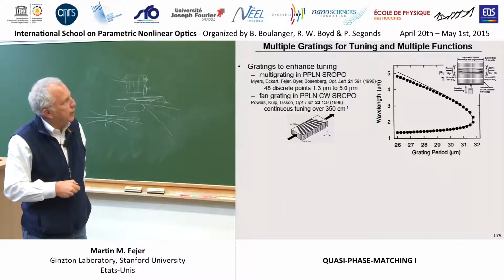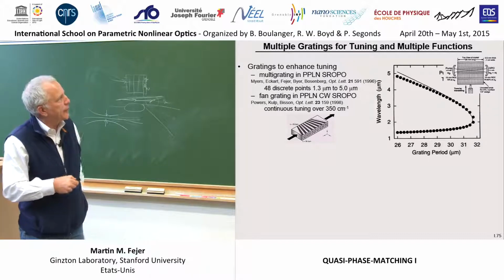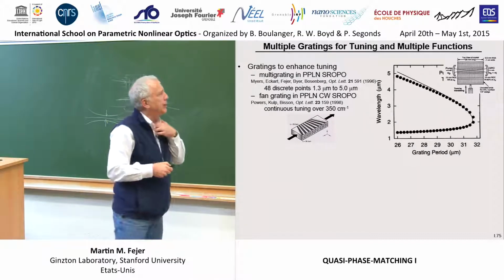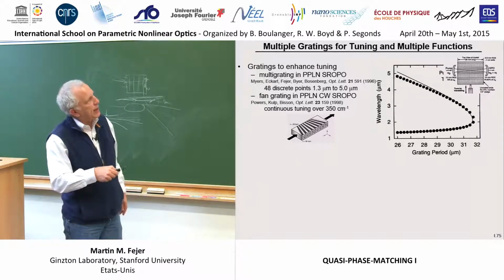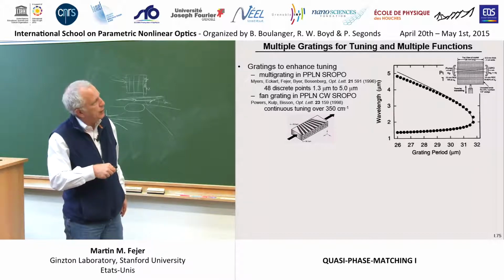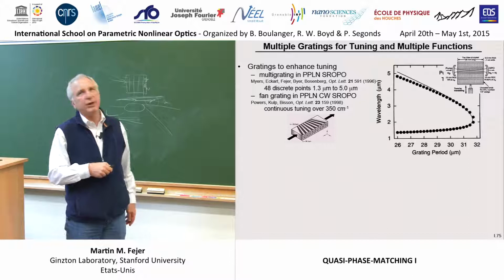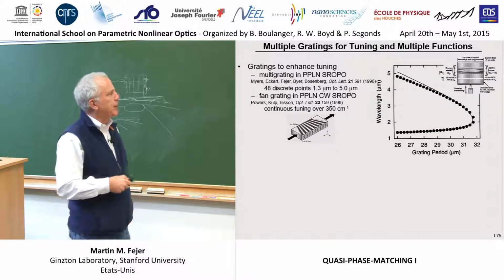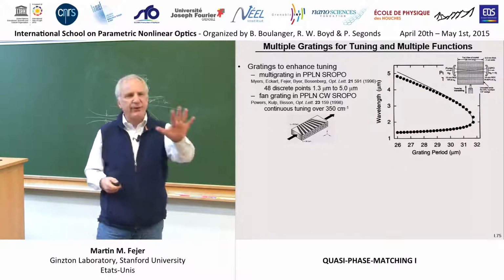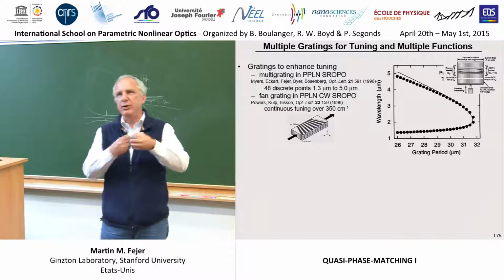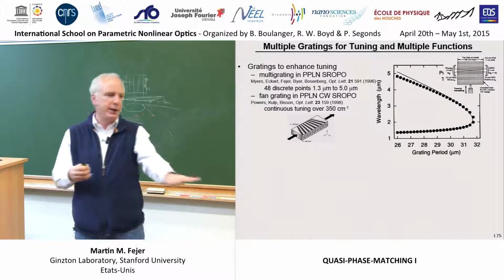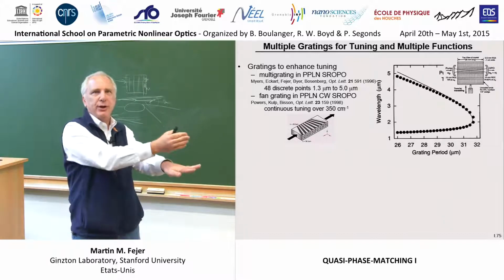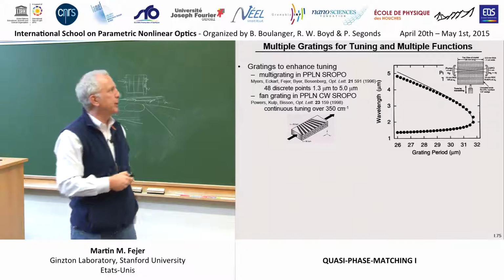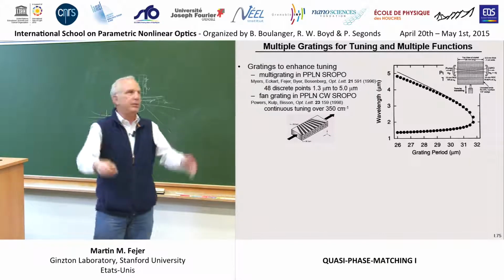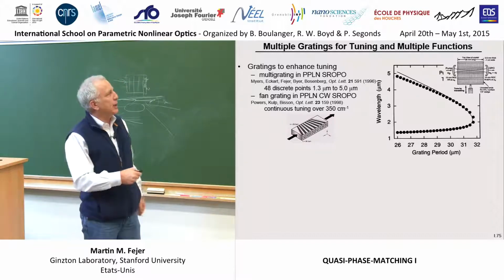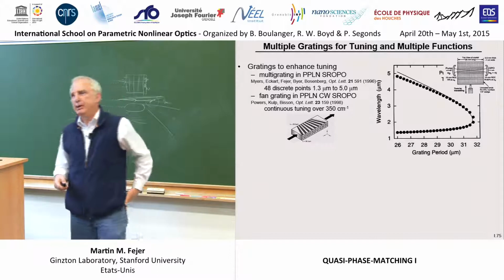If you want continuous tuning though, a fan-shaped grating, for example, first done by some guys at Sandia working with the Crystal Tech people. In this fan-shaped grating, you can do the same concept, but now as you translate transverse to the fan, you have a continuously varying period instead of a discrete period. The limitation in the case of lithium niobate is that fan angles bigger than about 5 degrees are hard to fabricate. The domains start to get erratic when you try to make the angles too far from those preferred orientations I was talking about. But up to about 5 or maybe a little more degrees, you can build that structure. So if you have enough aperture available, and since you could in principle use 3-inch wafers, you can get a pretty big range of periods even with a 5 degree spreading angle.